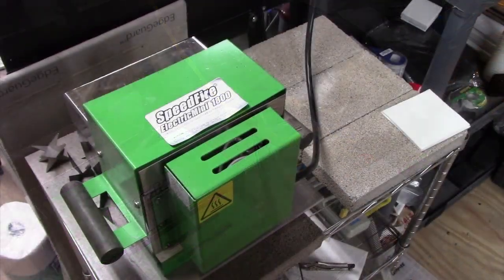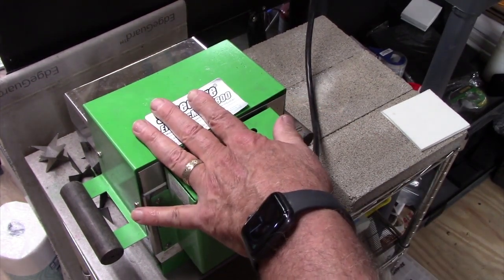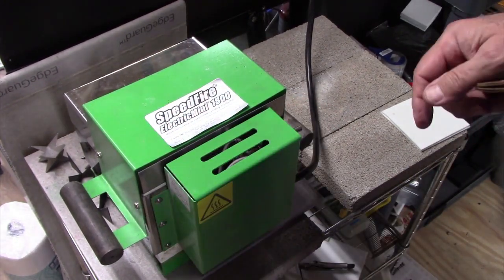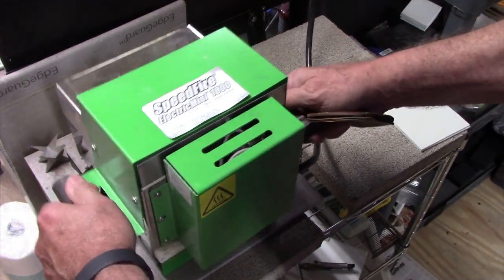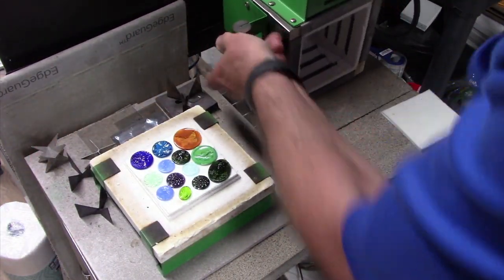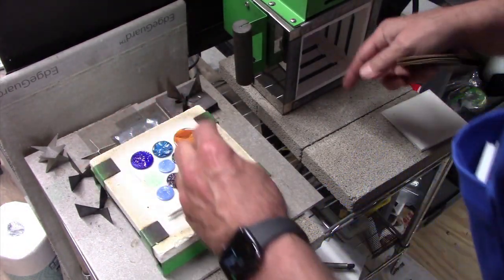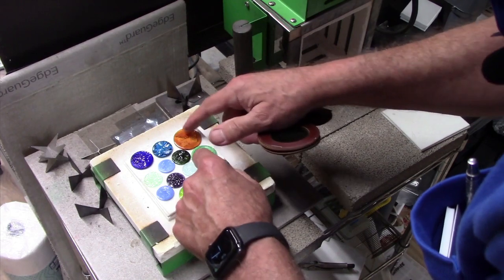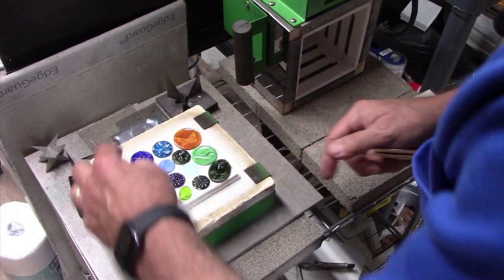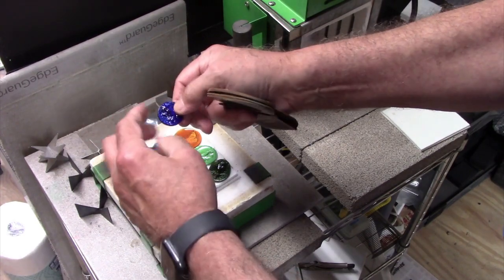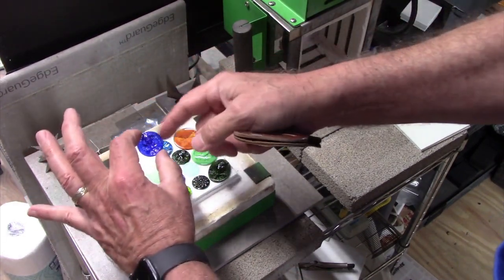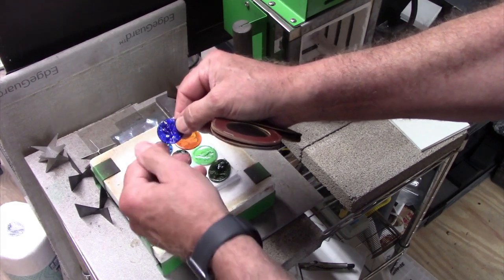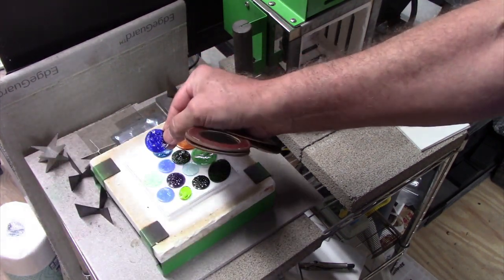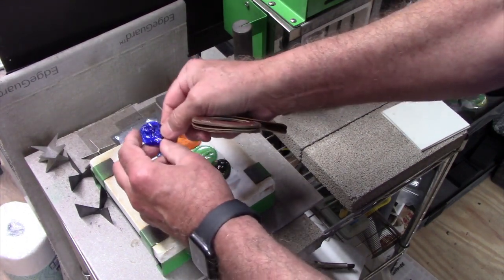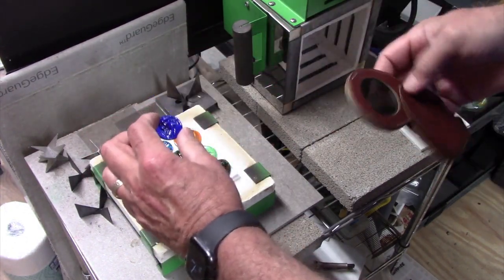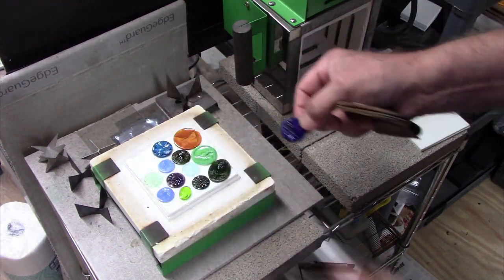Well, it's been about 6 hours. The kiln came back down to room temperature, which up here in the studio right now is about 80 degrees. So we'll see what we have. Well, nothing cracked tremendously. Have some dust that came off the refractory material. Everything's looking like it didn't explode. That's a good thing. So let's check out our Pompey made in that beautiful transparent cobalt blue and see if we've eliminated the Maltese cross that indicated that there was some internal stress. Even though it was distributed reasonably well, we wanted to get rid of that. And then I'll check these others too.